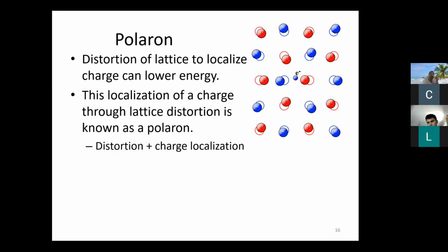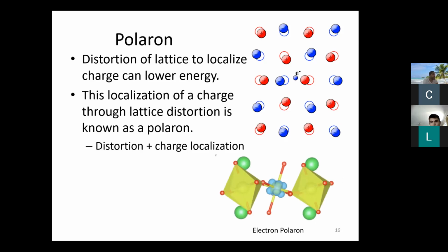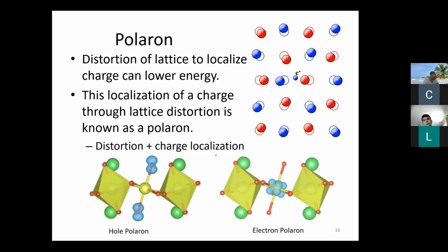So it's this distortion plus a charge localization. And depending on the range of localization, you call it a small polaron or a large polaron. And so here's an example of an isosurface of the charge density for an electron polaron. If you can notice, the oxygens look like they're pushed further away from the centerpiece, right? And so this electron is actually localized, in this case, on a cesium atom. And over here is a hole polaron. In this case, the hole polarons are actually localized on the oxygens, which are red.